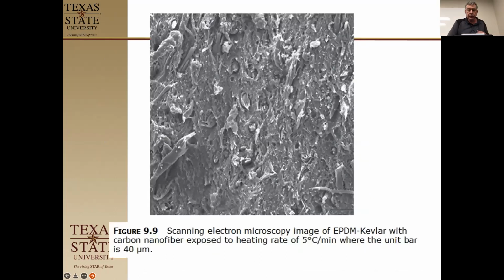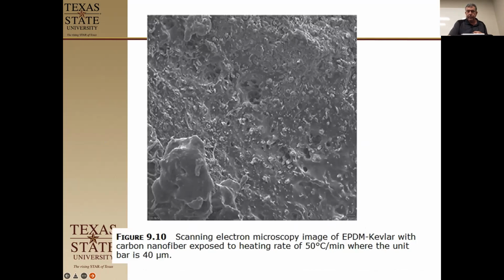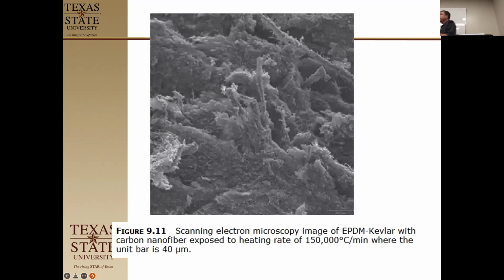Okay. So then they did another one with the carbon nanofibers exposed to the heat rate. And then they did another one with just the Kevlar at 50. That didn't look any worse. And then they did it with the rocket motor. And the rocket motor looked completely different than the two others, the 5 degrees a minute for the TGA and the 50 degrees a minute TGA. When exposed to this 150,000 degrees per minute, right here, we get a completely different structure. You have pyrolized fibers, a lot of porosity, a lot more. It's eaten down into the cave. Your surface roughness is much higher.